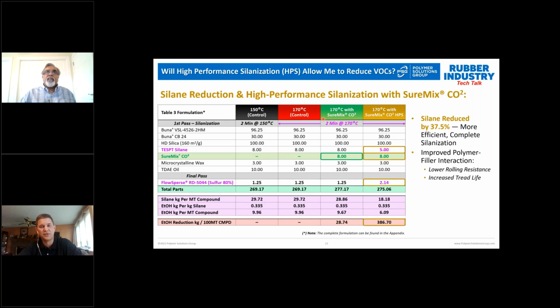And then the other thought we had was, if we can go to a higher temperature with silica and silanization using SureMix CO2, does that give us the opportunity to reduce the amount of silane in the compound? If you think about it, it's a typical reaction, right? If you're able to drive it further by going to a higher temperature, then you may not need as much of one of the reagents because you can get a higher degree of reaction.